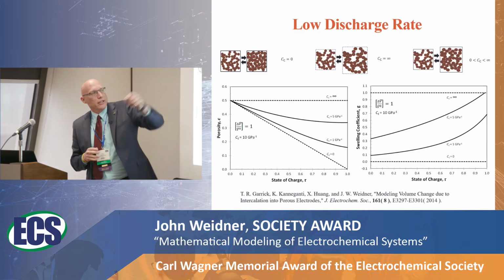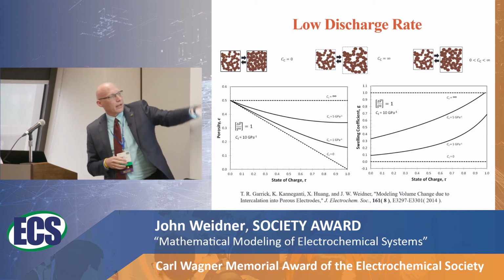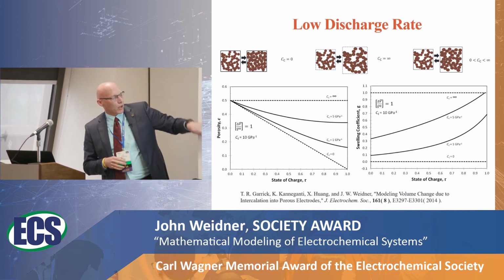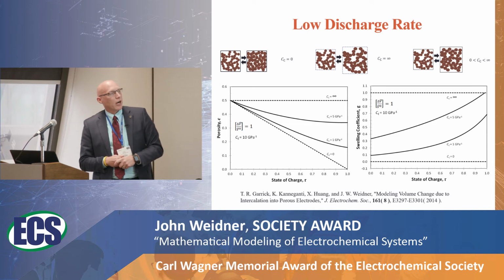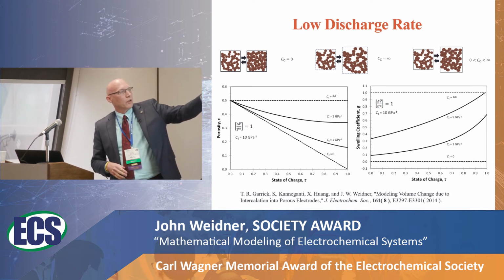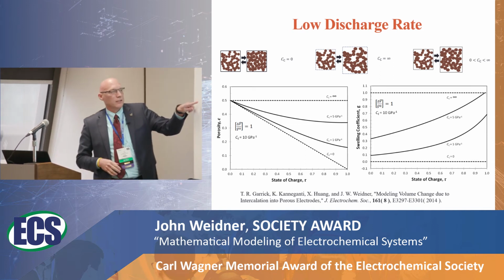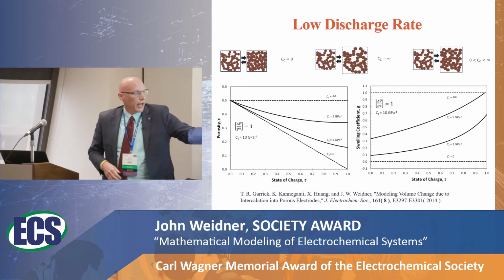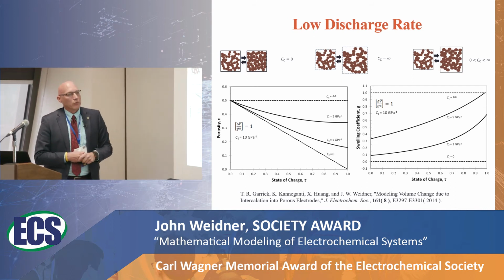On the other end, if there is no resistance to expansion, then all that volume change, there'll be no porosity change. And so if we look at the prediction of porosity versus state of charge, we find out that, again, if it offers no resistance, the porosity will remain constant. If it's a rigid can, it'll change linearly with time.